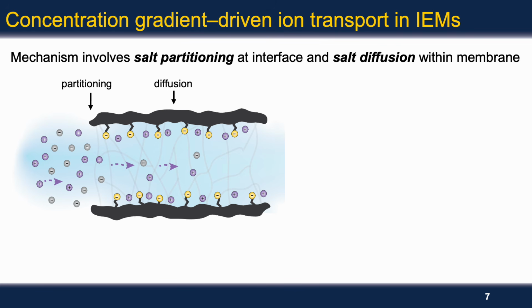To better understand what's happening in our concentration gradient-driven experiments, we have to turn to the fundamentals of transport in these membranes. The mechanism for transport involves partitioning at the membrane solution interface and subsequent diffusion across the membrane. When you have a concentration gradient as the driving force, the ions that partition into the membrane have to be electroneutral. So for every anion or chloride ion that sorbs into the membrane, there has to be a sodium ion or a magnesium ion or a counterion that sorbs with it. These ions then diffuse as a single entity across the membrane to maintain electroneutrality. And so for concentration-driven experiments, we talk about a salt diffusion rather than an ion diffusion.